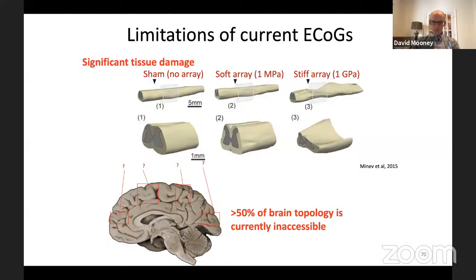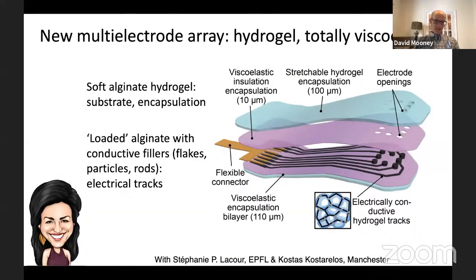So what Christina Tringides in the laboratory proposed then was a new type of multi-electrode array that would be based on hydrogels, would be totally viscoelastic to match precisely the mechanical properties of the underlying tissue. So the electrodes themselves would be viscoelastic, the encapsulation material would be viscoelastic, the whole thing would be viscoelastic, and we would exploit the ability of conductive fillers, things like conductive flakes and particles and rods, to provide the electrical tracks.